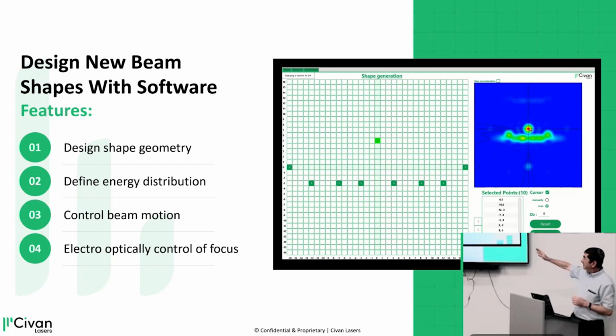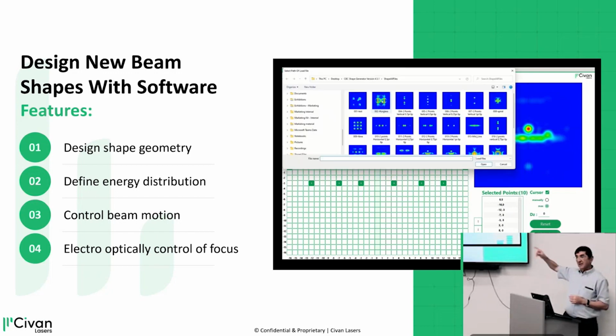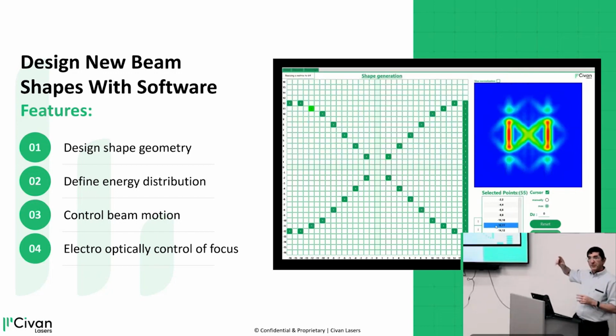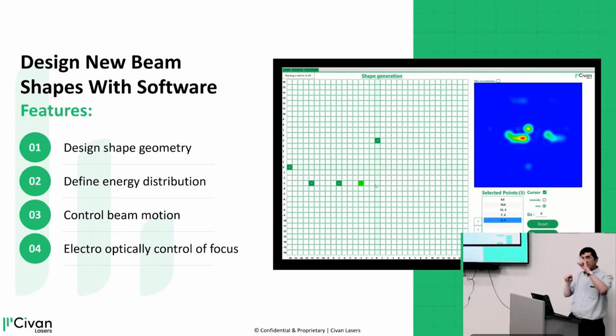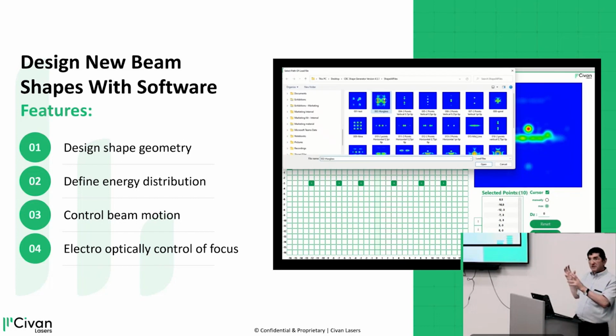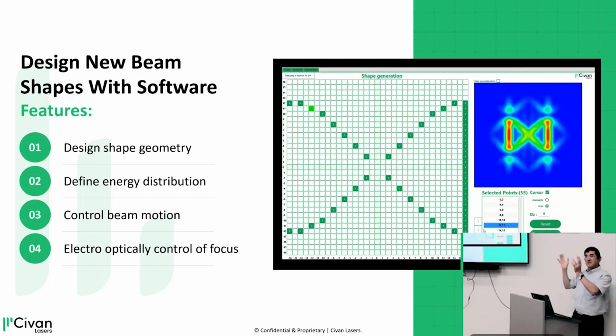And then you can also tell the laser how to go from point to point, because it's completely arbitrary. You don't have to go in some continuous motion. You can jump from this point to this point to that point, or you can have a few points at the same time. Completely arbitrary control on how to distribute this 32 kilowatts of the laser inside the melt pool. Very easy to use. Takes 1 or 2 minutes to design any beam shape that you want.